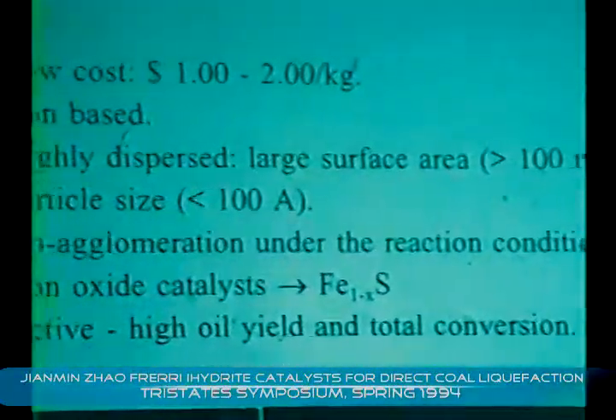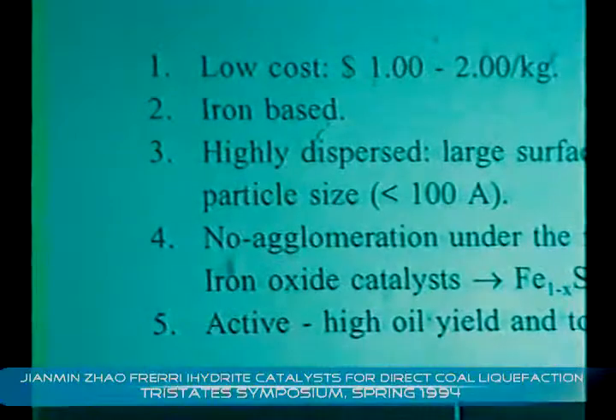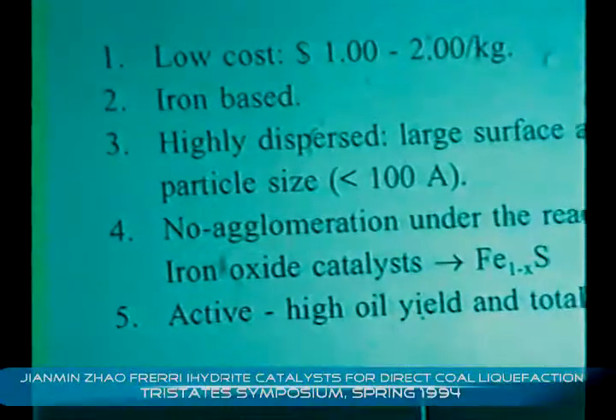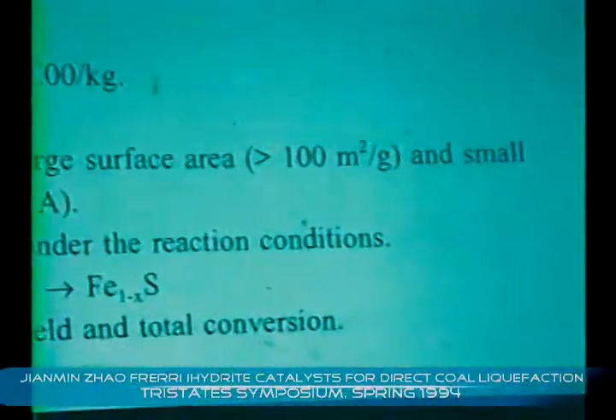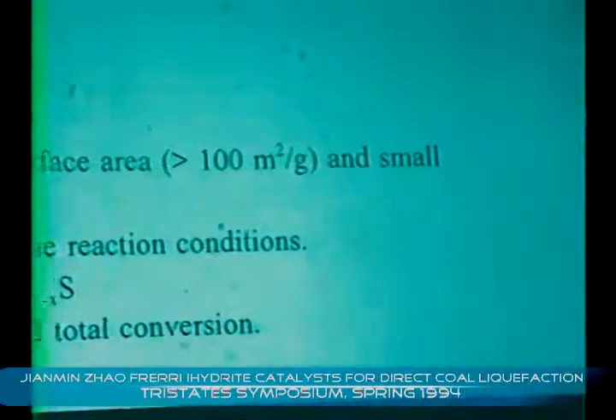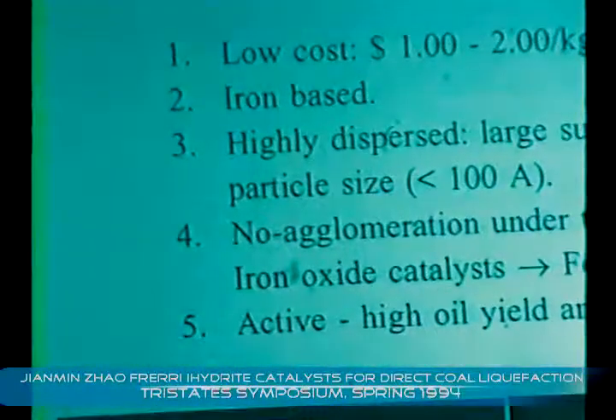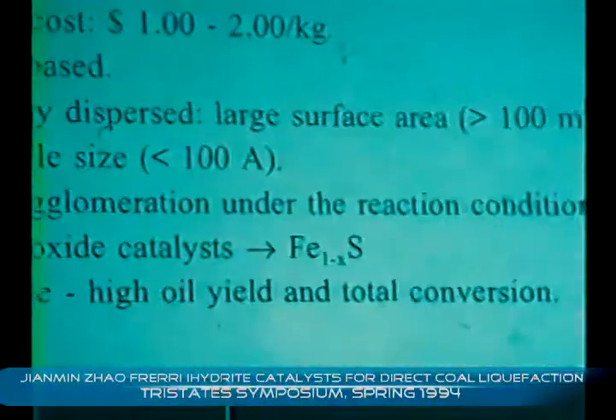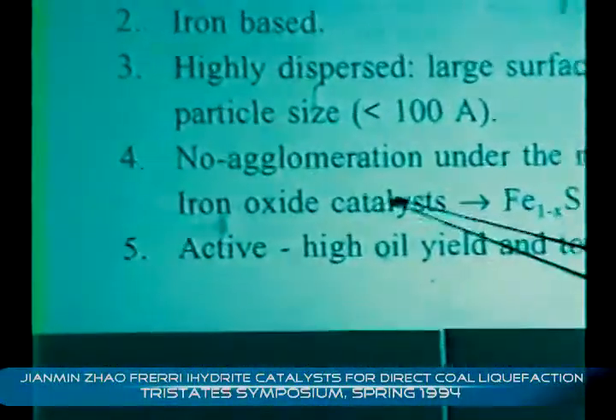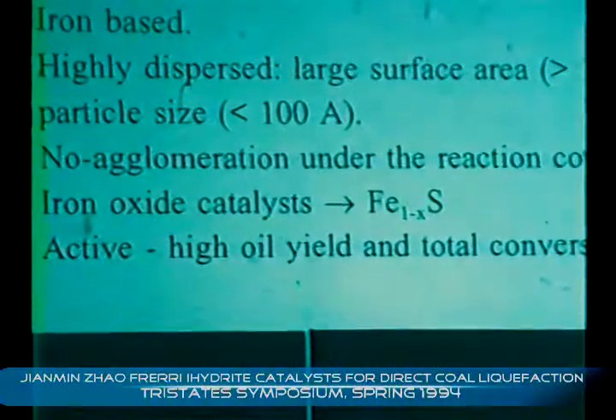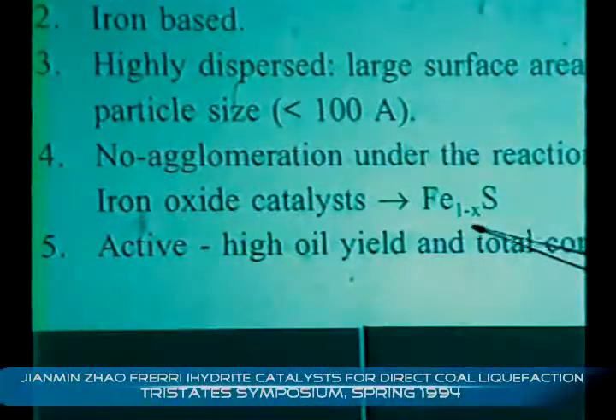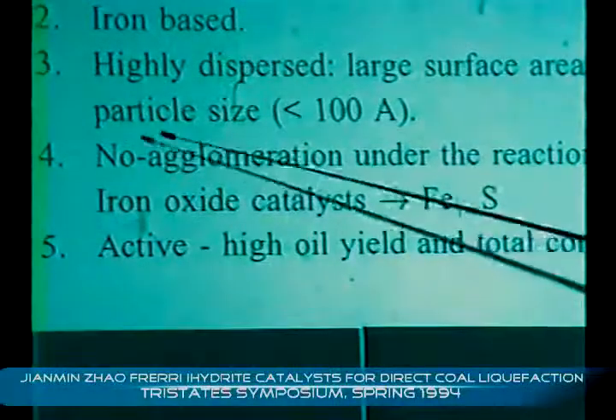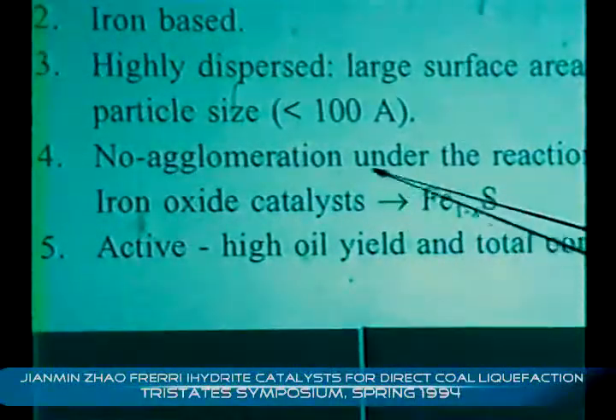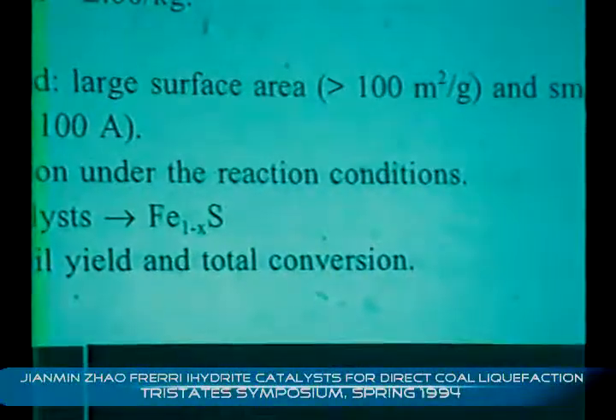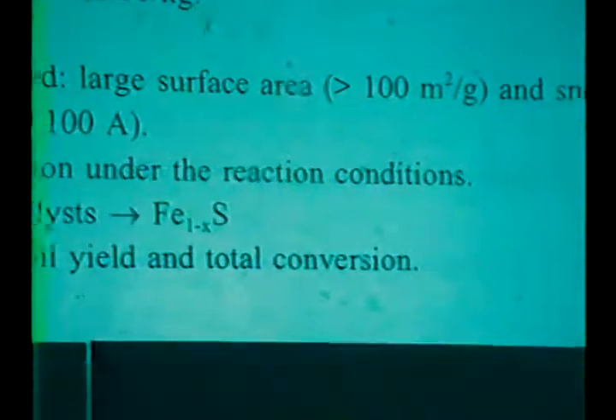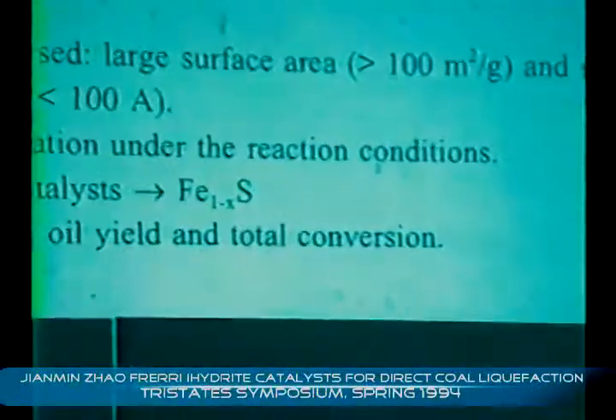So we have no choice but iron. As we can all understand, if the catalyst is highly dispersed with a large surface area with small particle size, probably we can increase the activity and decrease the loading. Since the iron catalyst we are talking about is usually a catalyst precursor, during reaction it converts to pyrrhotite. So we hope there's no agglomeration under the reaction conditions, and active means high oil yield and total conversion.